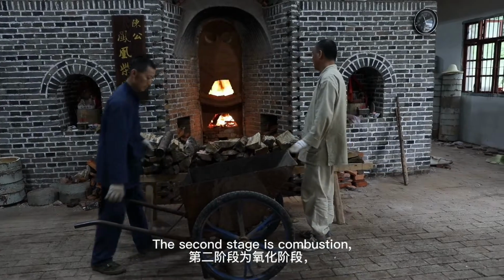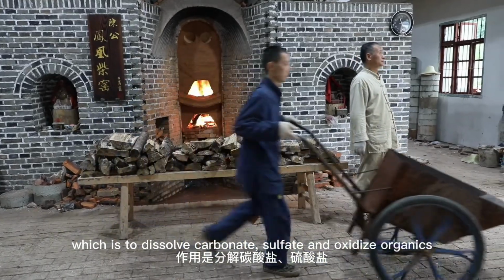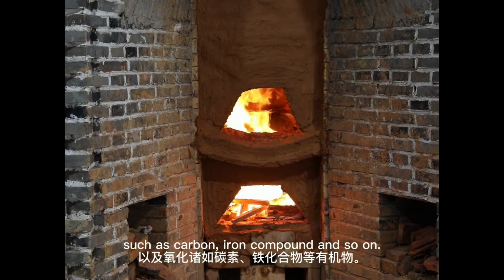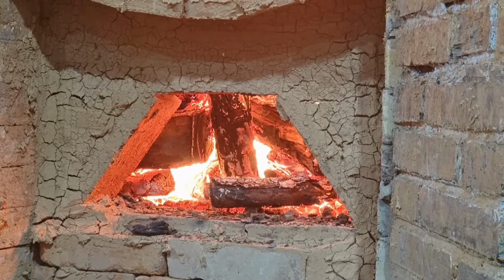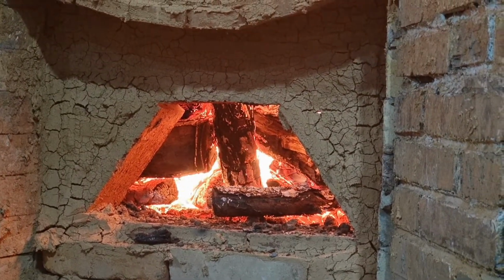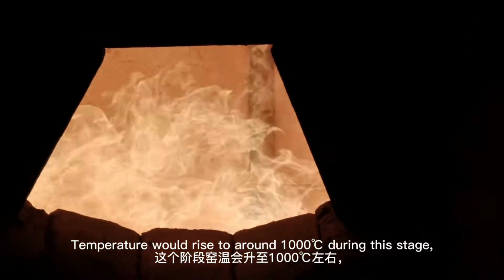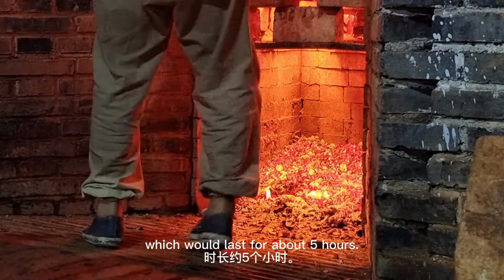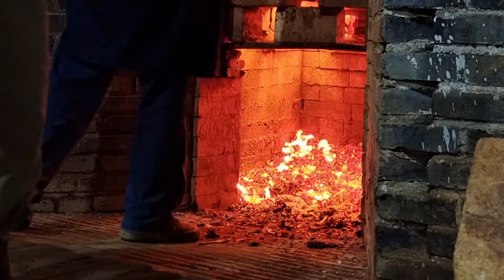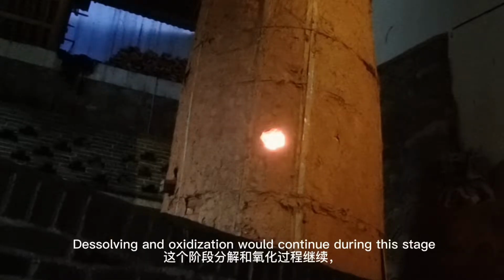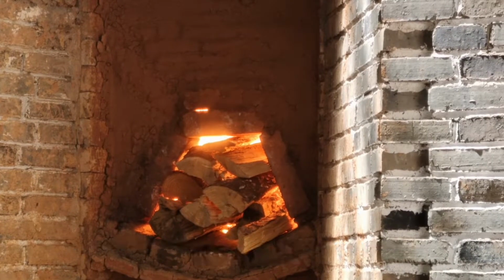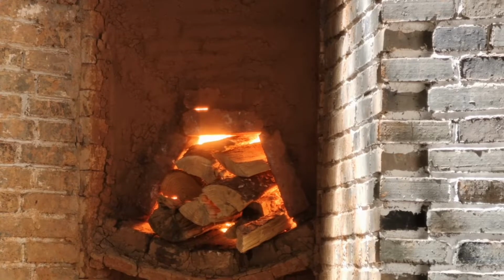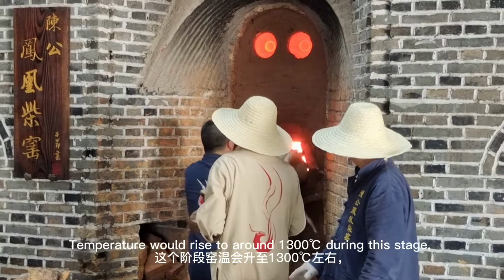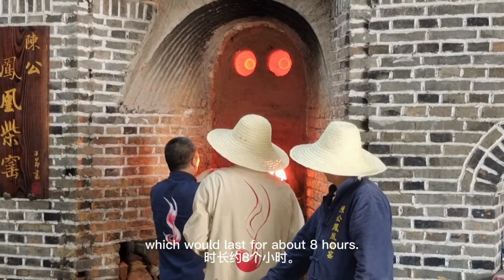The second stage is combustion, which is to dissolve carbonate, sulfate and oxidize organics such as carbon, iron compound and so on. Temperature would rise to around 1000 centigrade during this stage, which would last for about 5 hours. The third stage is reduction. Dissolving and oxidization would continue during this stage and greenwares would be transformed into porcelains. Temperature would rise to around 1300 centigrade during this stage, which would last for about 8 hours.